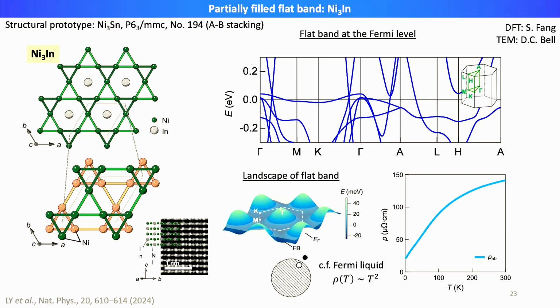Right. So before we go to the experiments, already from first principles calculations, you can see that one of the most prominent features in the electronic structure is the flat electronic states across the in-plane two-dimensional Brillouin zone located here. And this is a magnified view of the landscape of the flat band itself.